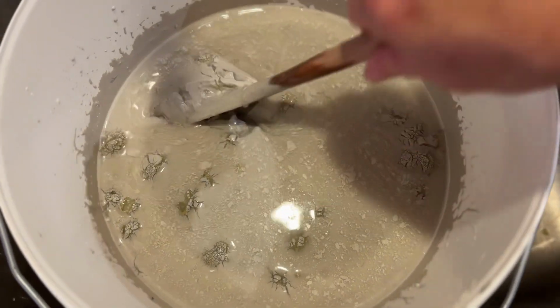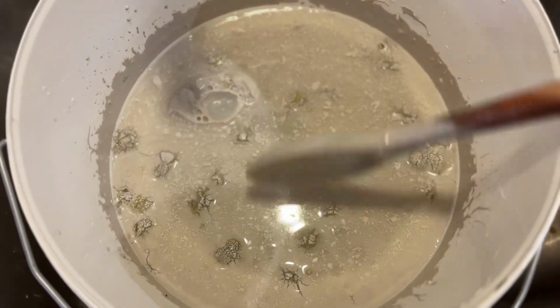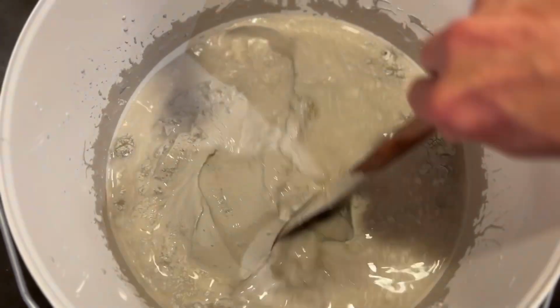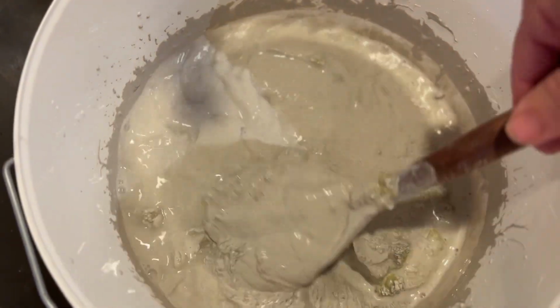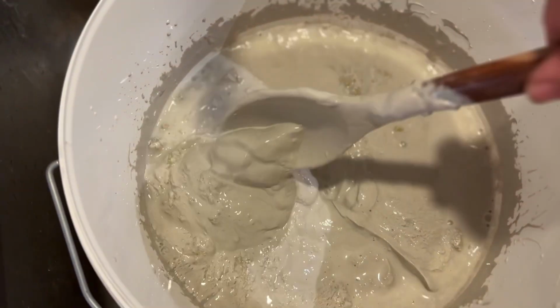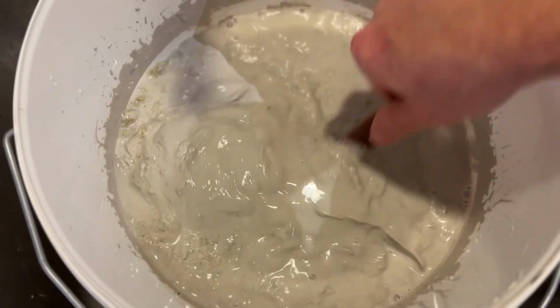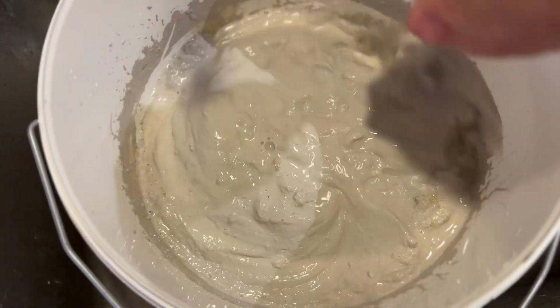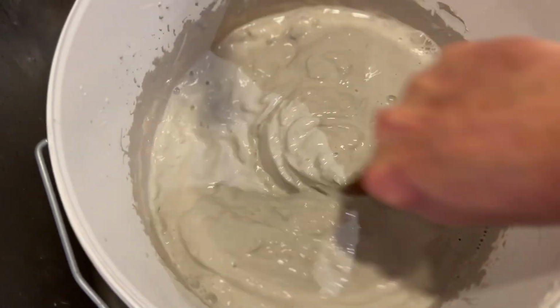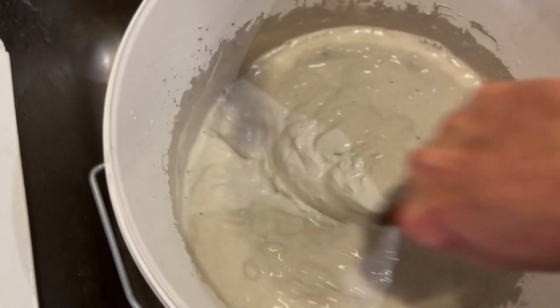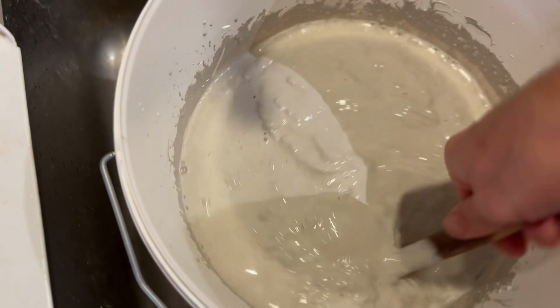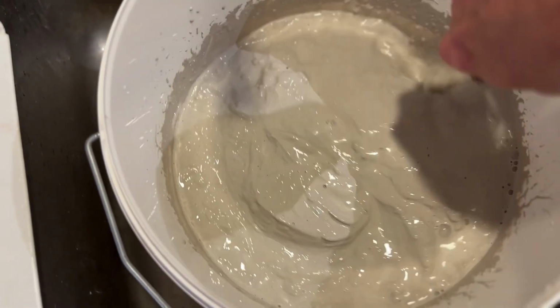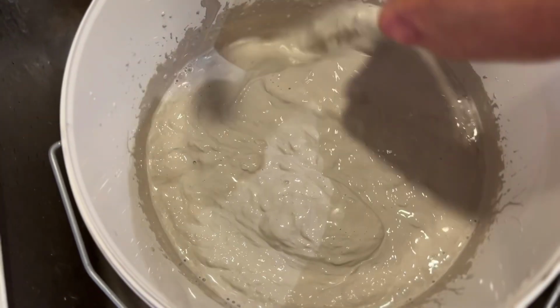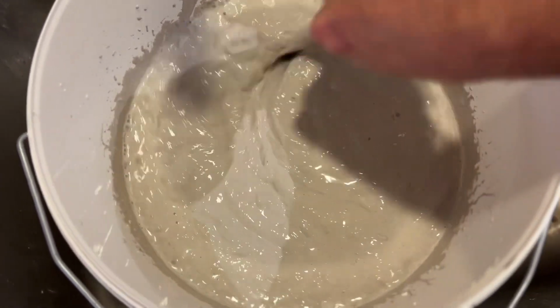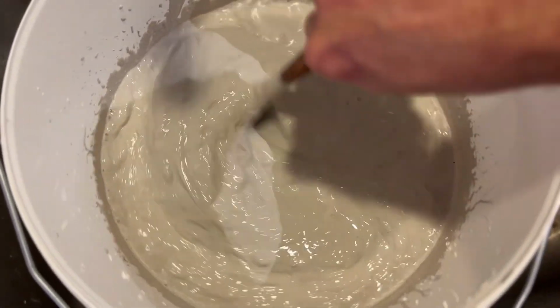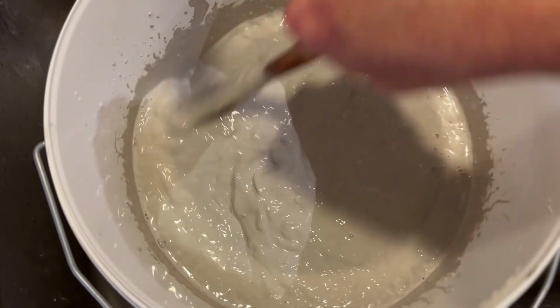As you can see, it has now settled some water on the surface, but also you can see it didn't settle the way that I just talked about with a hard bottom. It's just sort of muddy now, but it's easy to mix around. And that is due to the bentonite that we added. So it's always good to add that. And it's going to stay almost like that, even if you leave it for a few months. It's going to be this easy to mix up.